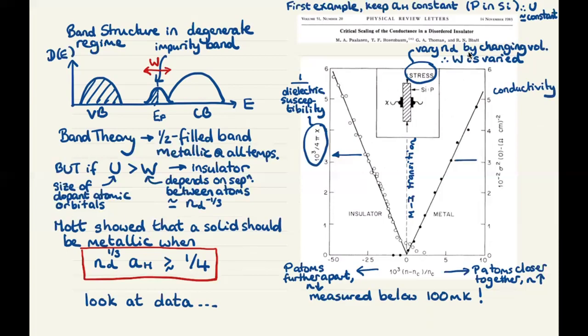And the black dots are indicating the conductivity. And we see that as the atoms are moved closer together, the conductivity is increasing. So we see exactly what we expect: when the atoms are far apart and the bandwidth is small, the system is an insulator. As the atoms move closer together, it becomes a less good insulator. Its dielectric constant is increasing, indicating an approach to metallicity. And at some critical dopant concentration, it undergoes an insulator to metal transition.